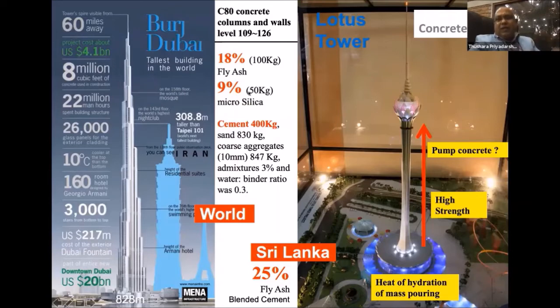On the other hand, when you see Burj Dubai, this is just one example of using this material. So I'll just go into it. As a thumb rule, if you want durability, you have to use around 25 to 30% of pozzolanic material. I think the Professor will share more. Like fly ash, pozzolana, it's good to have 25% of total cementitious material. I should tell, because total cementitious material in this example means they have used fly ash and microsilica.